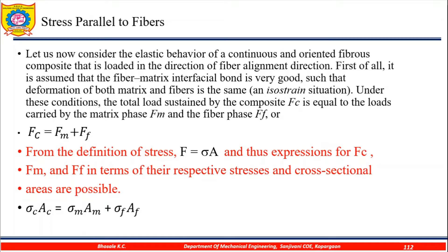So, Fc will be equal to Fm plus Ff. From the definition of stress, F equals sigma A, and thus expressions for Fc, Fm and Ff in terms of their respective stresses and cross sectional areas are possible. We put up the value here and then we get sigma_c times A_c equals sigma_m times A_m plus sigma_f times A_f.